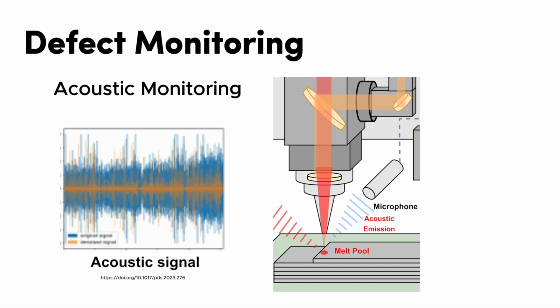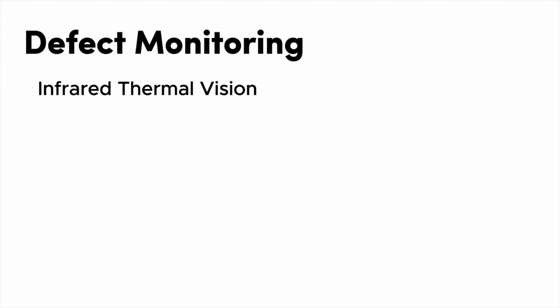In this method, the hypothesis was that ambient audio can be digitally removed and the sound of the machine can be isolated. Then, using machine learning, the acoustic sensor can determine whether the part has crack propagations via differences in audible feedback to the sensor. By comparing the resonant frequency of the part without cracks to the part with cracks, theoretically this method of defect monitoring is achievable. Another method that has been used for monitoring defects has been infrared thermal vision.